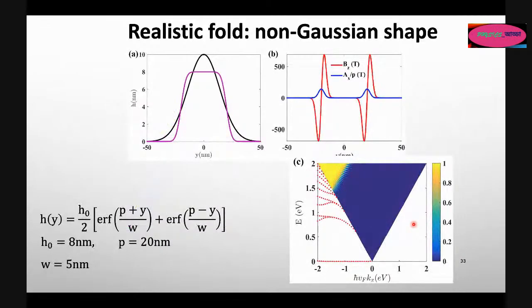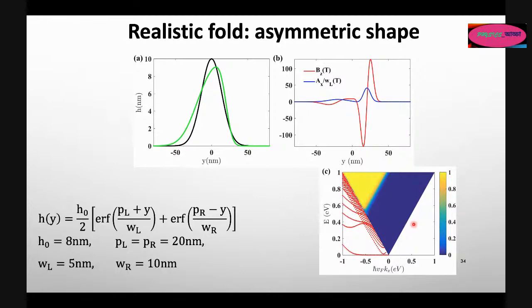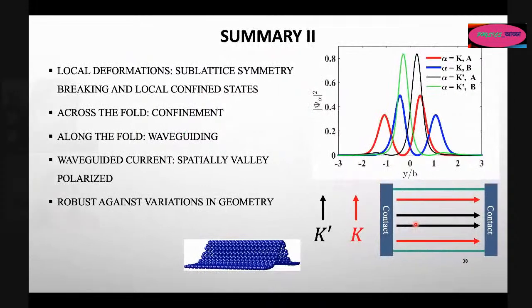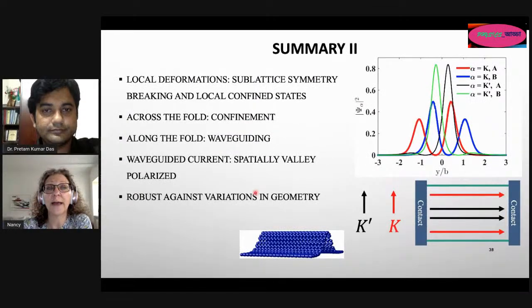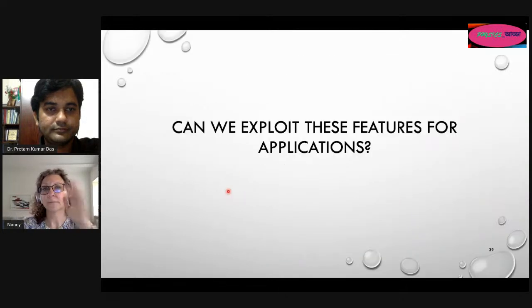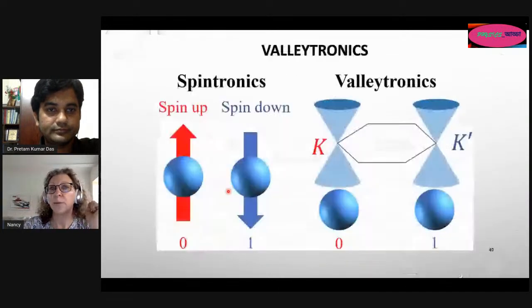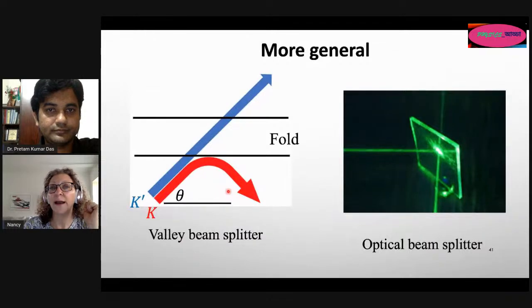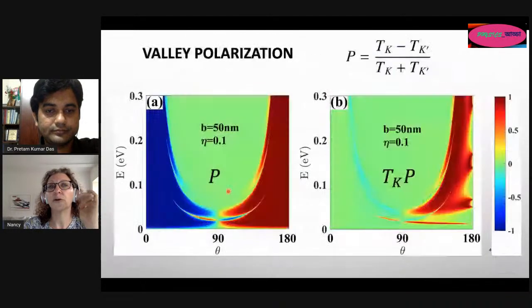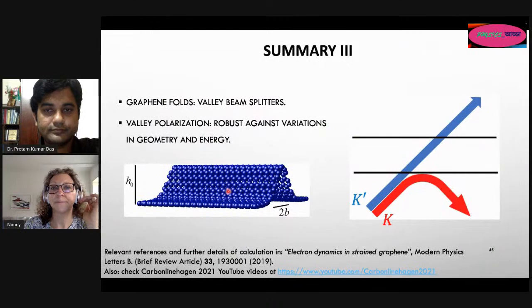So we check what happens if the shape is not Gaussian, what happens if the shape is not symmetric, and in all these cases, we find that folds are able to confine and at the same time are able to contain extended states that move along the fold, and that's what we call wave guiding. So these features are exploited for Valleytronics, and sorry about that, but I will skip this.